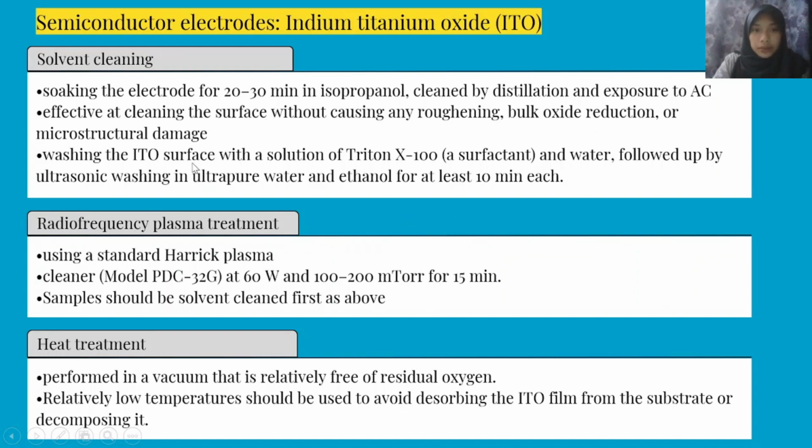So, washing the ITO surface with a solution of Triton X-100, a surfactant, and water, and it is followed up by ultrasonic washing in ultra-pure water and ethanol for at least 10 minutes each.